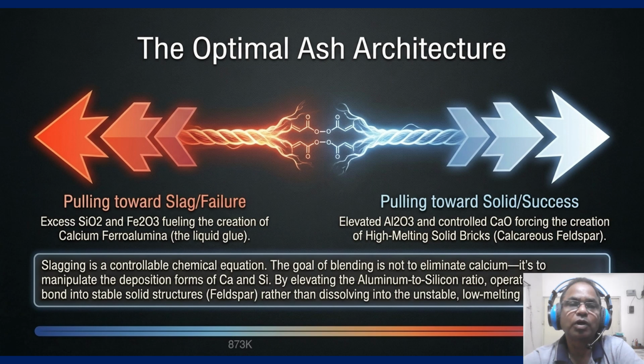You force the calcium to bond into stable, high melting feldspar bricks rather than dissolving into the unstable glue. The so what is that the goal of blending is not to eliminate calcium, it is to manipulate the deposition form of calcium and silicon. So we are effectively engineering out the slagging mechanism by architecting a more robust molecular structure that can withstand the heat of the raceway. So we implement this architecture through the three-step strategic playbook for the furnace.